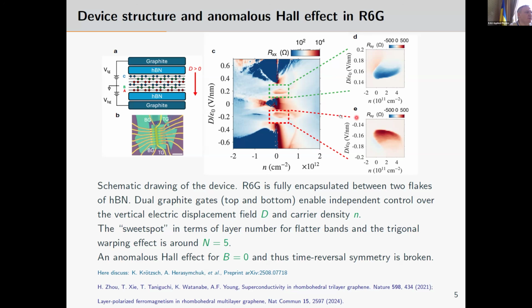And to say in a few words, for anomalous Hall effect, you usually dream to create quantum anomalous Hall effect for realizing Hall conductivity standards without magnetic fields. This is the kind of goal of playing with these materials. And as I say, trigonal warping effects spoil the system, and it's believed that the compromise, when we have flat bands and they are not spoiled by trigonal warping effects, is around the number of layers 5.